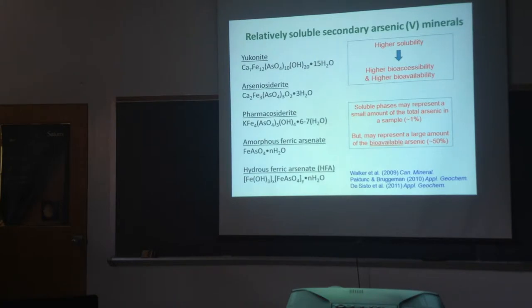So, as I mentioned, some phases turn out to be a lot more bioavailable than others, whether you measure it in live organisms in vivo testing or in stomach fluid simulations called in vitro testing. And it could be that you may have a small amount of something, say like pharmacosiderite or arseniosiderite in your sample. It might represent only 1% of the arsenic, but it may represent half of the bioavailable arsenic, just because it's so much more soluble and bioavailable in stomach conditions.